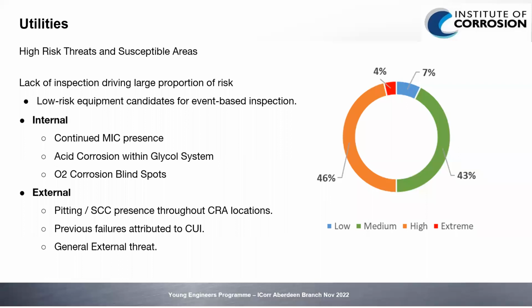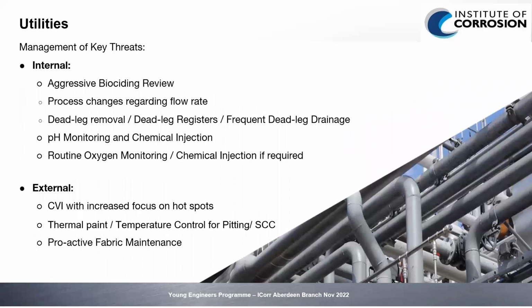We also have the threat of O2 corrosion, most notably in heating and cooling mediums. Once again, this is expected based on the fluid. Again, inspection data has been sparse in this area. And internally, we're looking at pitting and cracking presence throughout the CRA locations, with several instances where the operating temperature is on or above the pitting and cracking thresholds for these materials. As previously stated by Lewis, CUI is a massive issue on this asset, which I'm going to cover in just a bit. And finally, a general external threat similar to the process side.